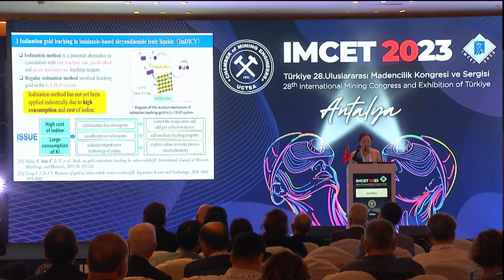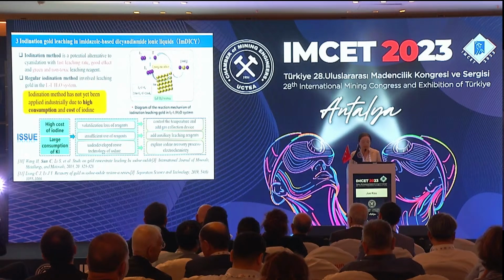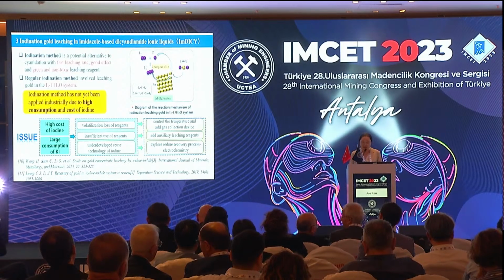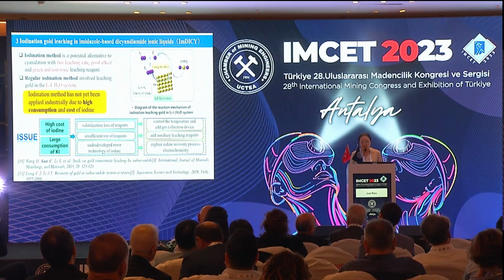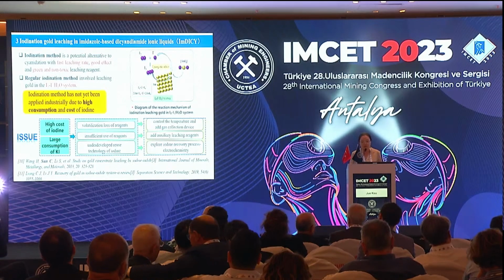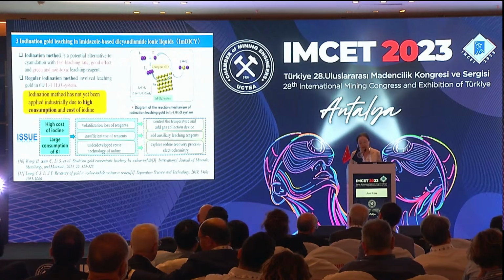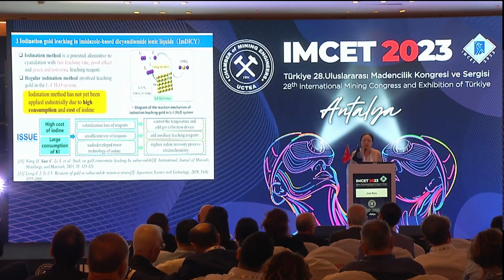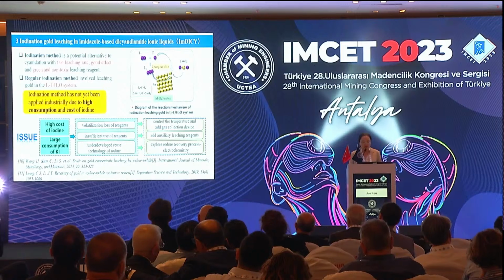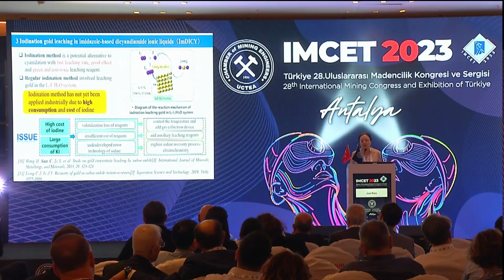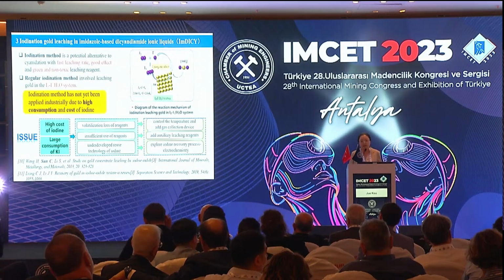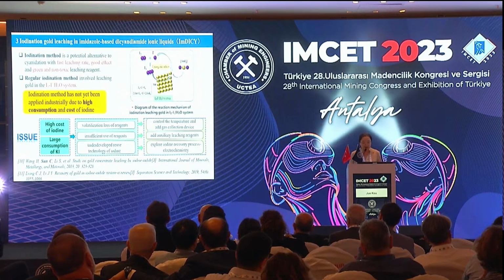However, it cannot be widely used because of the high cost of iodine. This is the result of volatilization loss of the reagents. Therefore, to get better performance, we have to control the temperature precisely and add a gas collection device to recover a certain amount of iodine. And also in this process, we need to add a large amount of potassium iodide to dissolve the iodine in the liquid. Therefore, it has a large consumption of potassium iodide.